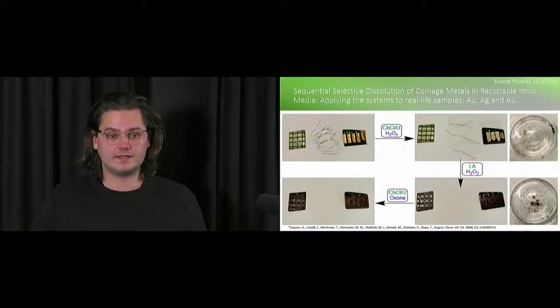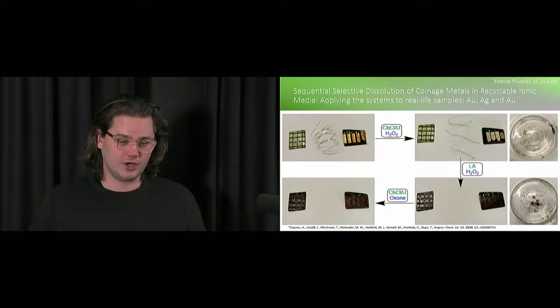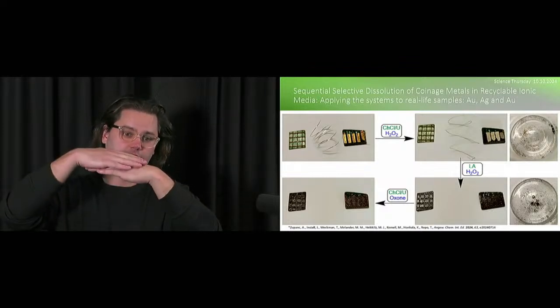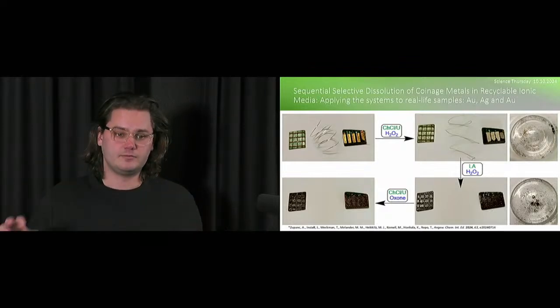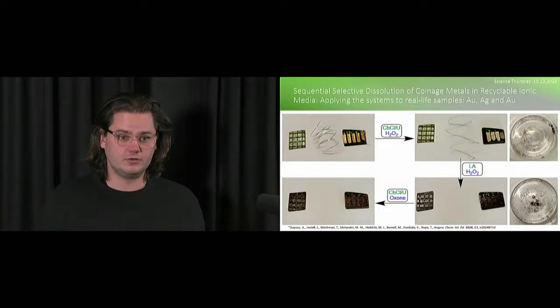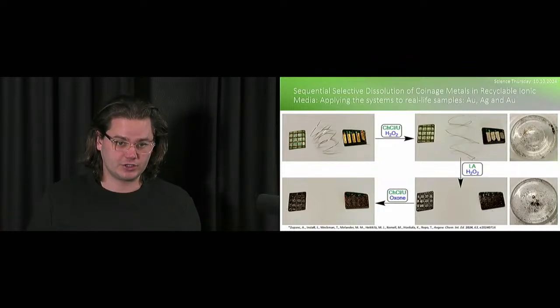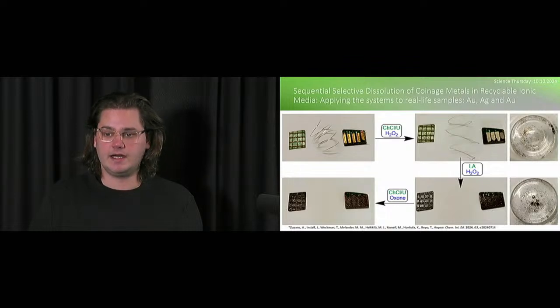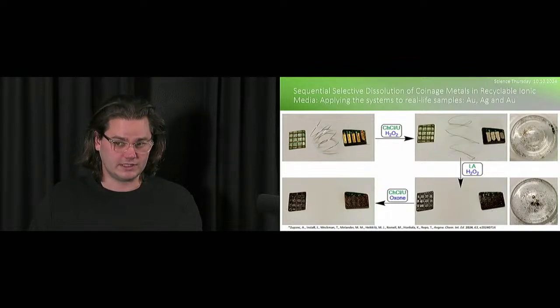What happens besides that is also that the copper below the gold connection fingers is dissolved, so the gold connection fingers essentially fall off, but they do not dissolve, so they were left in our reaction vessel that you can see on the right side of the slide. Then we could apply our system to dissolve silver using lactic acid and hydrogen peroxide, and still gold doesn't dissolve, as the method was designed for this.